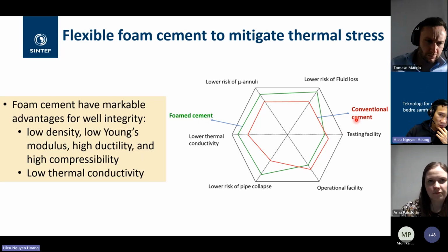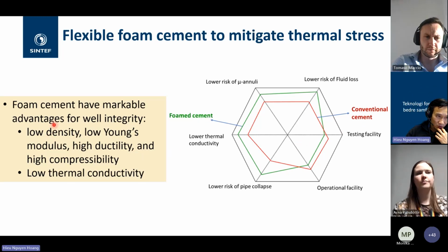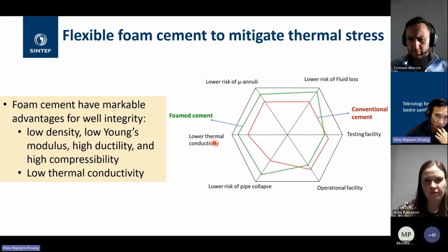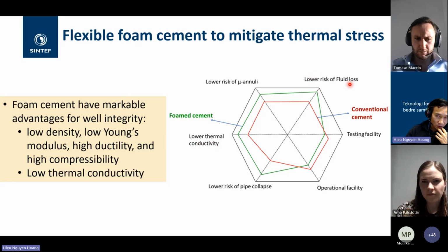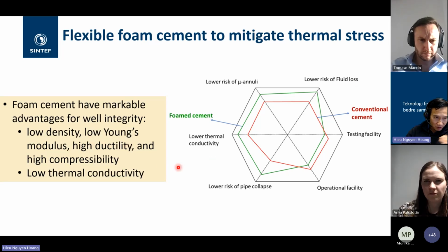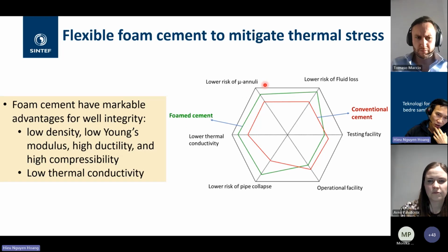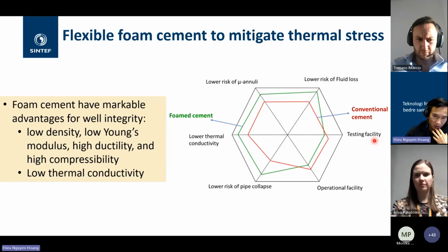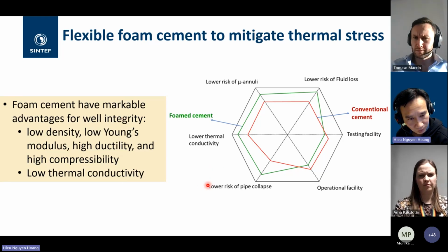In comparison to conventional cements, we see that the foam cement offers low density. It means lightweight, minimizing the risk of loss of circulation. We have a low Young's modulus to increase the flexibility, but at the same time we have high ductility and high compressibility. It means that we have a lower risk of cement fracture and a lower risk of microannulus creation. The only drawback is that this is quite a new solution, so the testing facilities are still not optimal yet. So we still do a lot of work to qualify and develop these solutions.